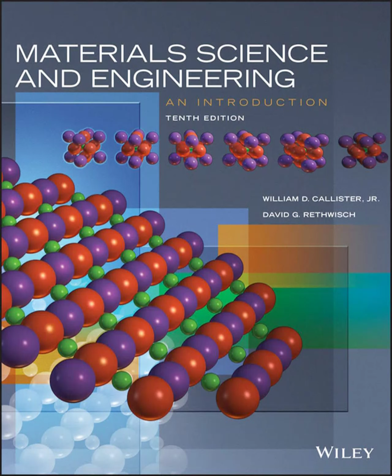Let's break that down. Cx is the concentration you get at a depth x after time t. C0 is the initial concentration everywhere in the material. CS is that constant surface concentration. And D is the diffusion coefficient. The error function part, erf(z), where z is x over 2 root Dt, well, its values are tabulated. You just look them up.